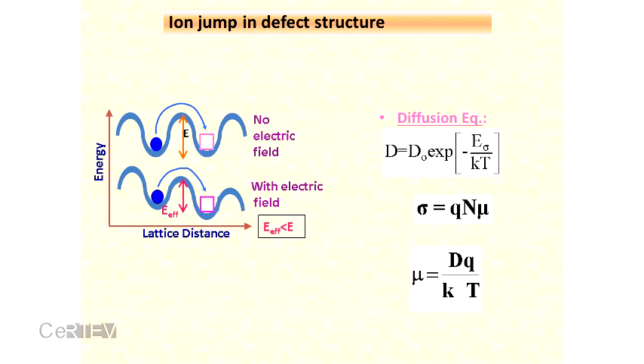mu. Then my question is, we can measure this parameter experimentally, but we cannot measure the charge carrier concentration and the mobility separately. So this is the main problem we face in studying ionic conductivity. For electronic materials, this was not the case, because by Hall measurement we can calculate the charge carrier density for electronic charge carriers, and mobility we can measure otherwise.